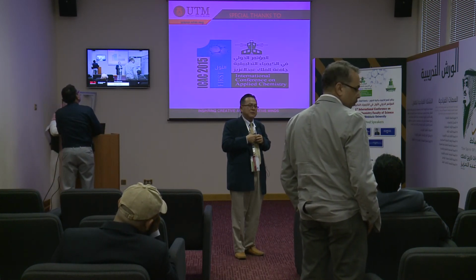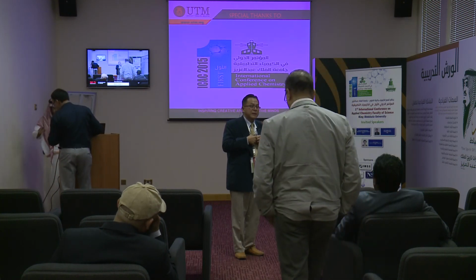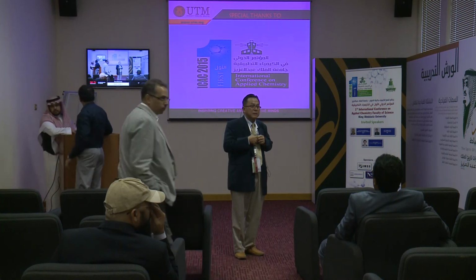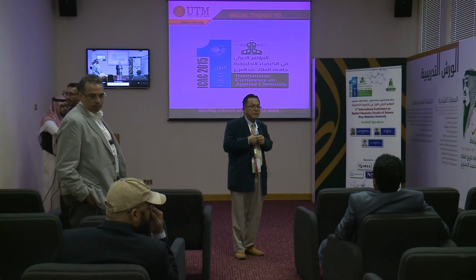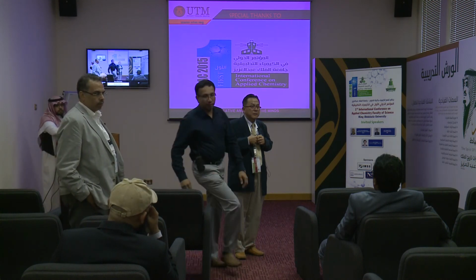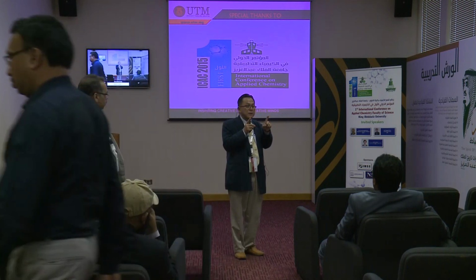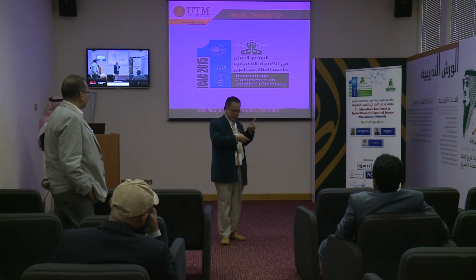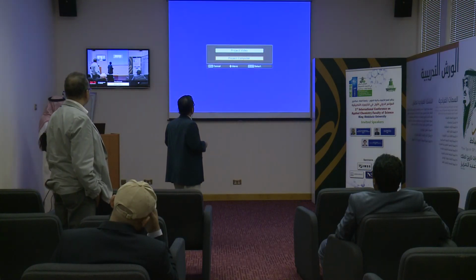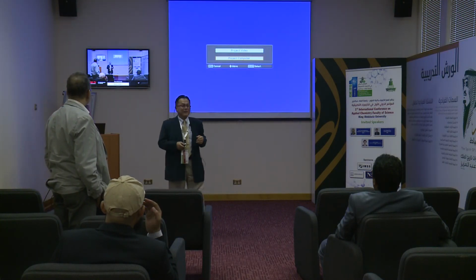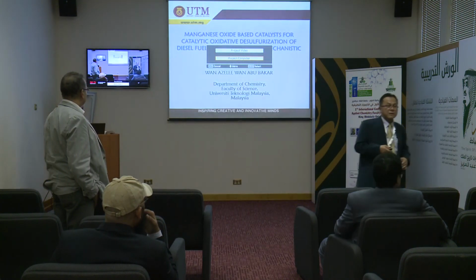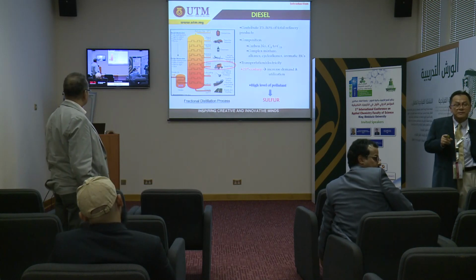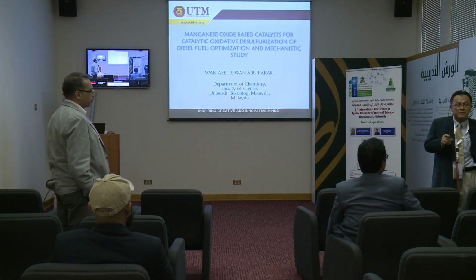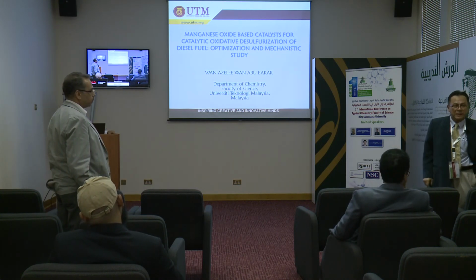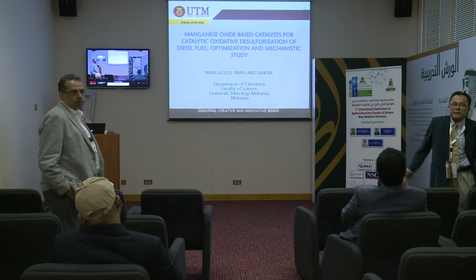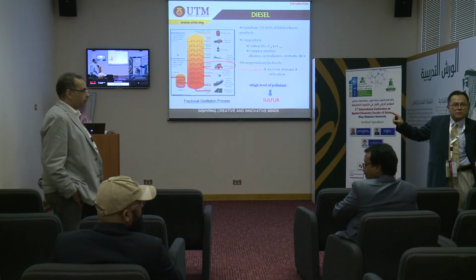And moreover, in the first step, as you had mentioned in the EDS, you are reducing the sulfur level in the diesel from 437, something like that, to 136. Whereas in the oxidative process, we have written from 90 to 47. What about in between 137 and 90? I can't catch you. Yeah, from 90.